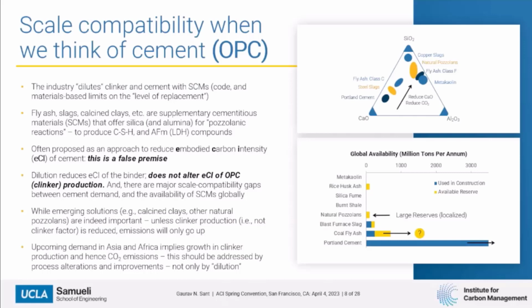We can use all kinds of things, right? We can use fly ashes, we can use slags, we can use calcined clays. The general idea is you're trying to initiate some sort of a pozzolanic reaction to produce CSH and the AFm, or the layered double hydroxide style of compounds. Keep in mind that this is often proposed as an approach to reduce the embodied carbon intensity of cement. This is a false premise. This is simply not true.